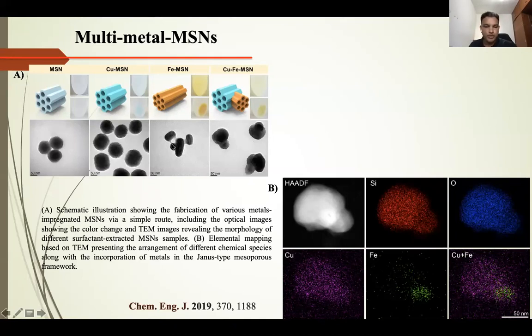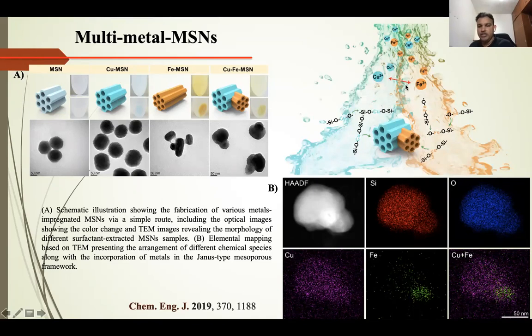So that led to this Janus ellipsoid. I mean, the ellipsoid shape of iron as well as the spherical shape of copper MSN led to Janus ellipsoid, differently shaped MSNs. Even this tries to create a large gap in the surface area, so that you can load more drugs inside. Whereas copper alone could create some level of ROS, if you add iron, the ROS levels increase. So it is really beneficial for us to have more. This is how it happened, where the repulsion between two positive metals would create a change in shape of the silica. So that's what the whole idea is.